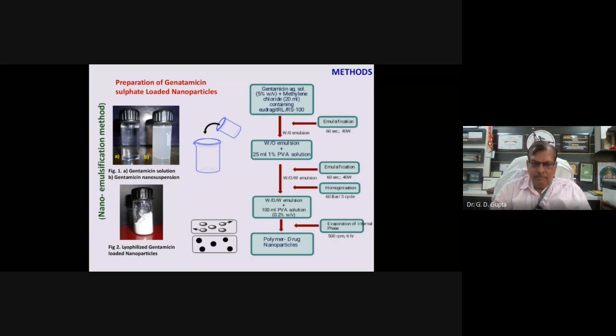In this case, we had used an aqueous solution of gentamicin, 5% weight by volume, and we had emulsified it in a solution of methylene chloride containing Eudragit polymer. Eudragit RS/RL 100 grade polymer was used, which is particularly used to control the release of the drug. This water in oil emulsion was prepared by the process of emulsification. Then after getting the water in oil emulsion, again the emulsification was done in 1% polyvinyl alcohol solution. Polyvinyl alcohol is nothing but a stabilizer.